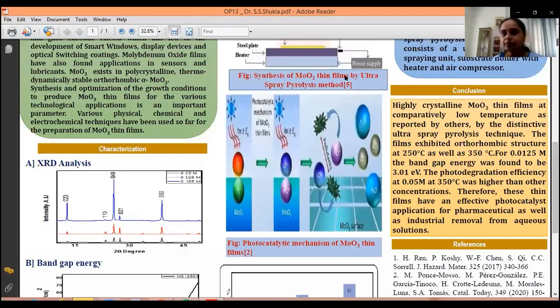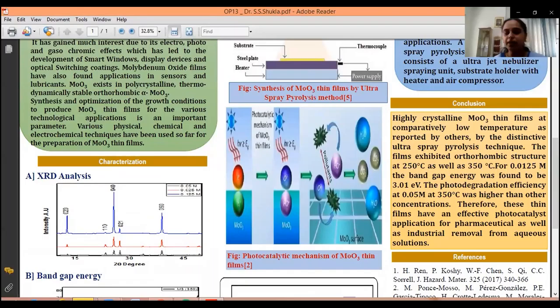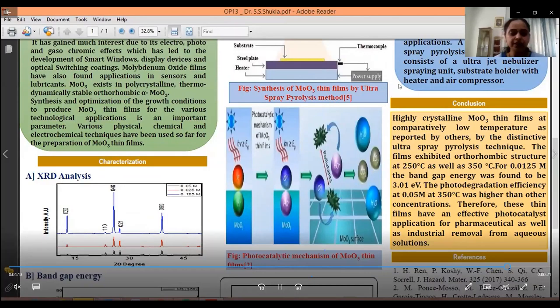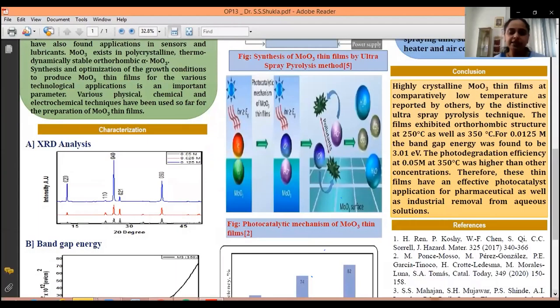Conclusion. In this study, we have demonstrated a mild and green route for the formation of molybdenum oxide thin films by the ultrasonic spray pyrolysis method. Their structural, optical and visible light-driven photocatalytic performance was investigated. The XRD and optical study showed the formation of alpha molybdenum oxide phase with nanocrystalline nature. The 0.05 molar thin film showed higher photocatalytic activity. As future scope, we also plan to study gas sensing applications for the thin films obtained.